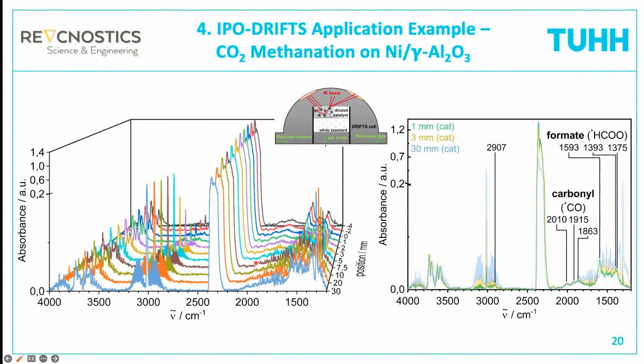And now in the next experiment, we fill our drift cell with a highly diluted catalyst. And to amplify the bands here, I have split the axis so that we can also see the low intensity bands. And you see again, the spectrum is dominated by the gas phase molecules, but here in this spectral region between 1,200 and about 2,000 wave numbers, there you see something that is different from the gas phase spectrum, and these are the surface adsorbates. And when you assign the bands, then you can see that we detect carbonyl species. There are 3 characteristic bands that can be assigned to carbonyl, and we also detect formate species. For example, this band here at 1593, this is very characteristic for bidentate formate. And also this band here at 2907, this is the CH vibration of this formate intermediate.